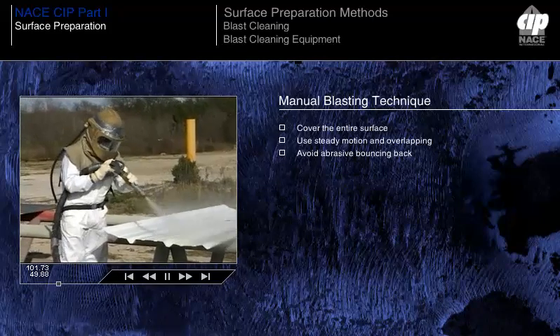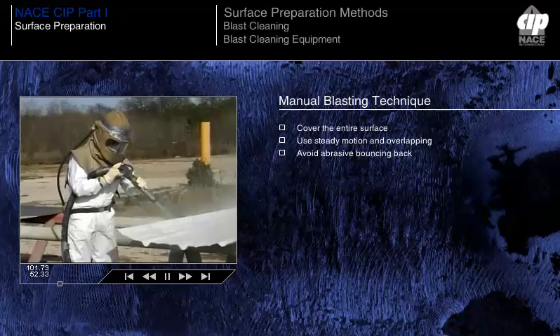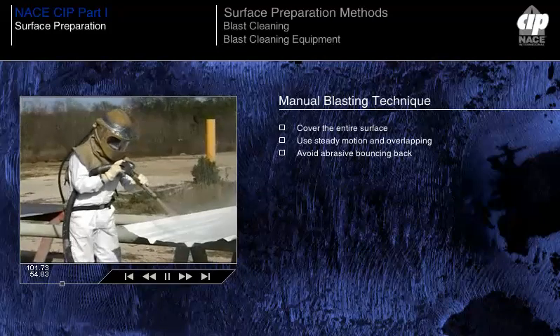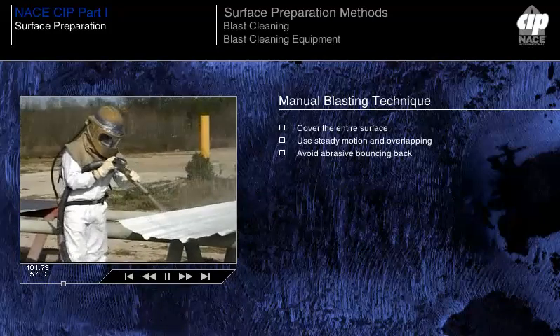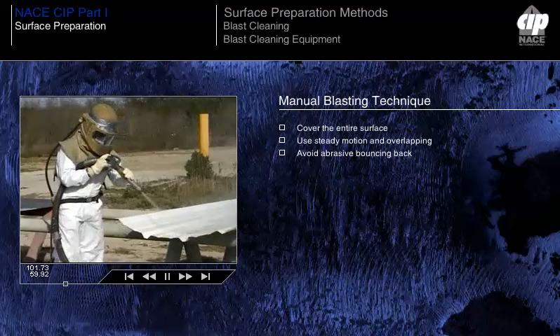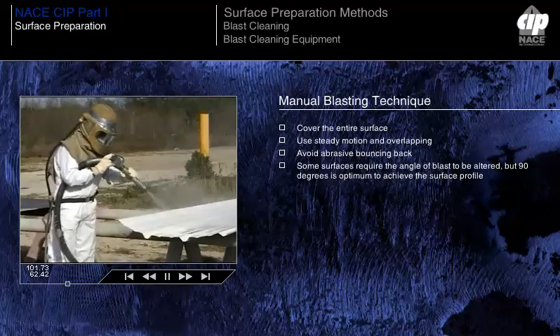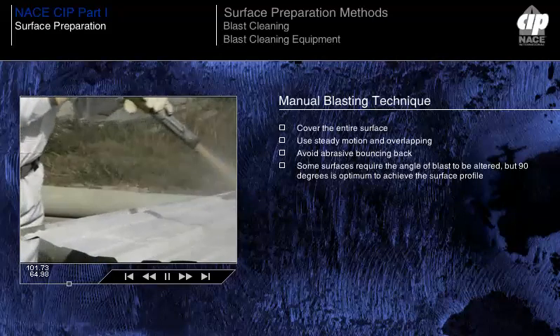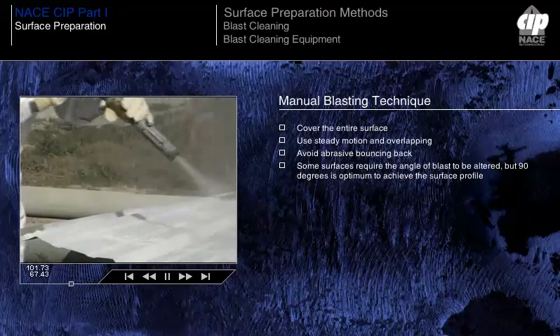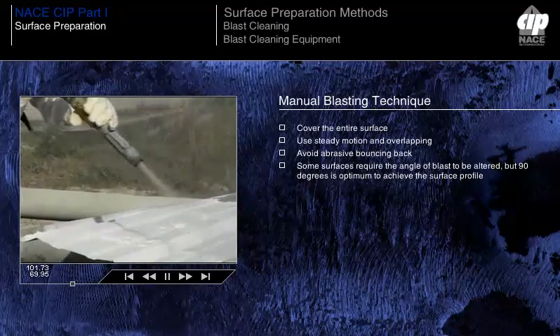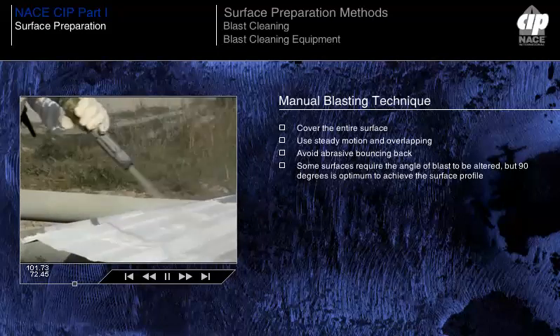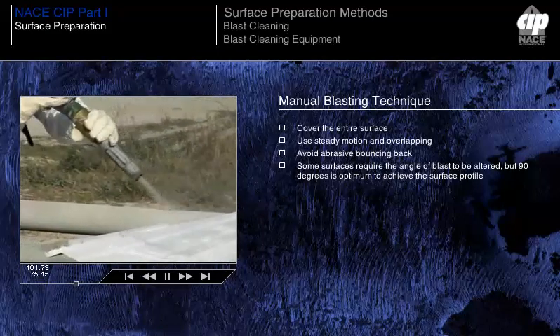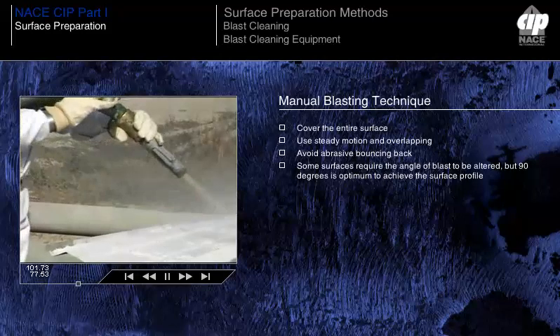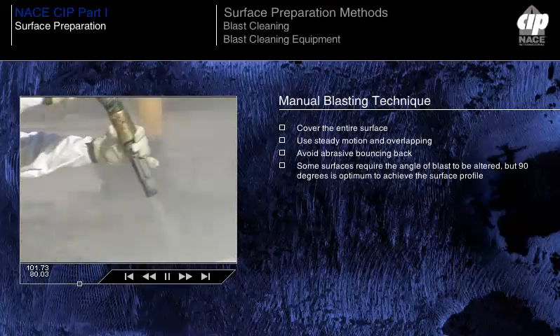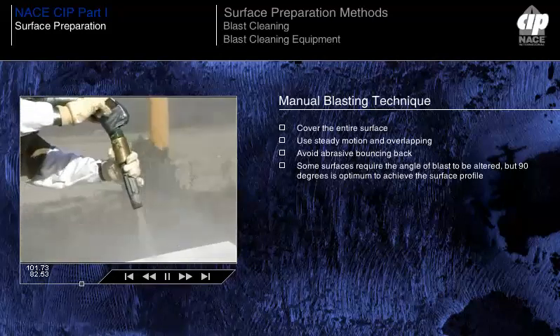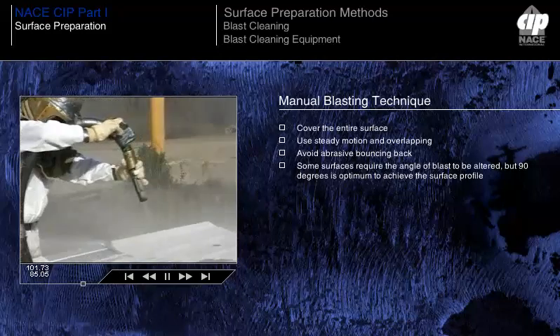Some surfaces, such as those with heavy mill-scale layers, or with coatings such as thermal sprayed zinc or aluminium, are best blasted initially at a shallower angle, for example 45 degrees. The operator must be aware that this technique, while efficiently removing the existing coating layer, produces a reduced surface profile due to the angle of impact. Final blasting at right angles to the surface is required if the correct surface profile is to be achieved.